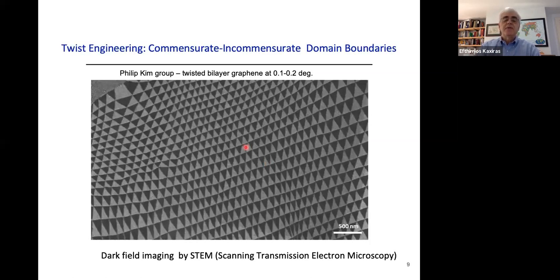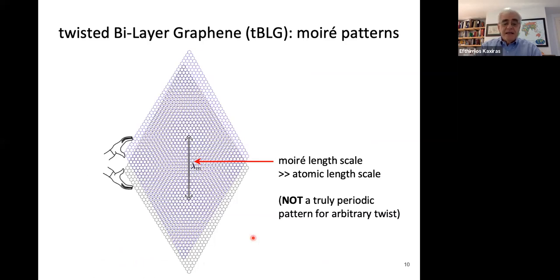And here's another example, a very large area of twisted bilayer graphene with a twist in the range between 0.1 and 0.2 degrees, again from Philip Kim's group. And what you see here is a dark field image by scanning transmission electron microscopy, revealing these patterns, and I will explain these that come from the relative twist. So basically what you see is a Moiré pattern from the two different layers.